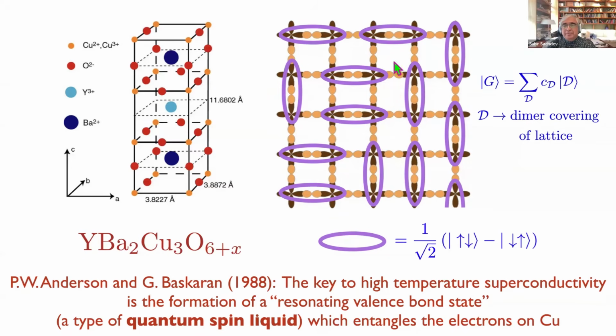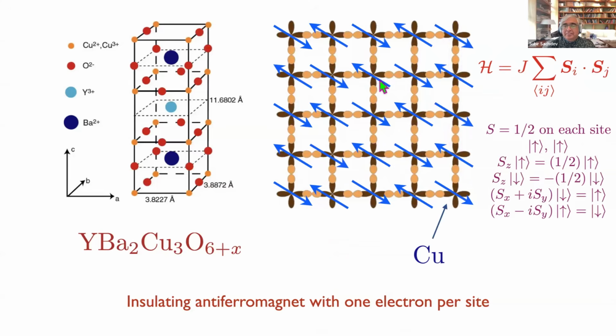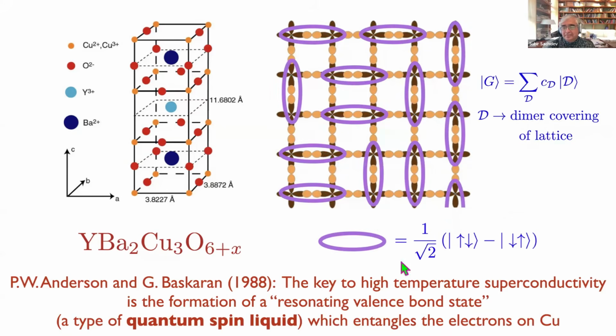So what he proposed was that the spins, instead of being anti-parallel as in this arrangement, if the spins are anti-parallel, that doesn't optimize the quantum energy. That is not the lowest possible energy for two spins. The lowest possible energy is obtained when they form a spin singlet, which is a coherent superposition of these two states. So you can certainly form spin singlets by pairing the electrons in some configuration. Each of these dimers here is then perfectly optimized, but the remaining ones are not. To fix that, he proposed the resonating valence bond state, which is a generalization of states that appear in chemistry for benzene and were also discussed by Linus Pauling, but here applied to an infinite lattice.